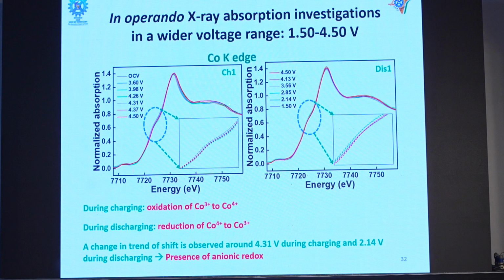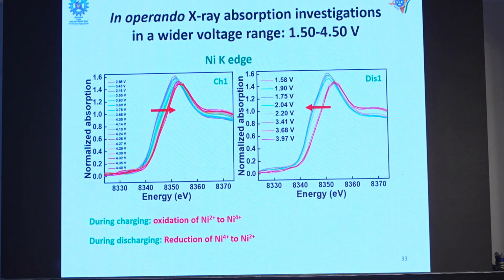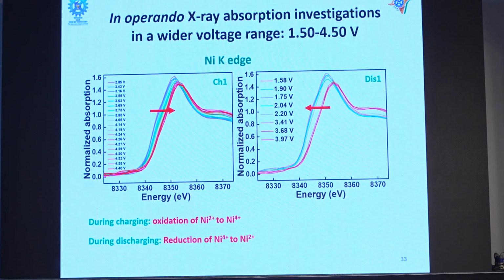But in the case of cobalt, we don't see any 2 plus. We see only the cobalt 4 plus to 3 plus electrochemical reaction. So just by decreasing the upper cutoff voltage, we are actually tuning the cobalt 2 plus reaction. Then for the nickel 2 plus/4 plus, this is the major electrochemically active couple in this particular voltage range, that is 4.5. So at 4 volt, we have manganese, nickel and cobalt 2 plus. And at 4.5, manganese is rare and cobalt is very minor and nickel is the only electrochemically active ion.